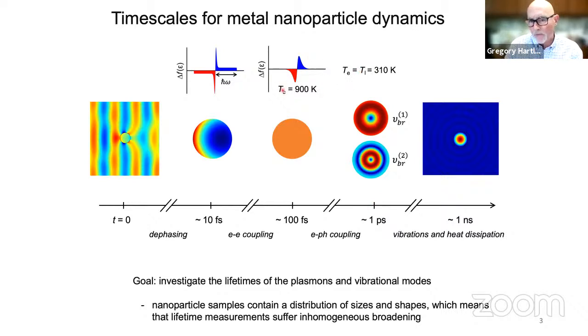And if you start with putting enough energy in to create a temperature of the electrons of about 900 Kelvin, when they reach equilibrium with the phonons, you'll get about a 10 Kelvin temperature rise in the lattice. So this is my very quick picture of what happens with the interaction of light with metals. You get this very rapid heating of the lattice, and the temperatures that you create are on the order of a few Kelvin to tens of Kelvin in typical experiments.